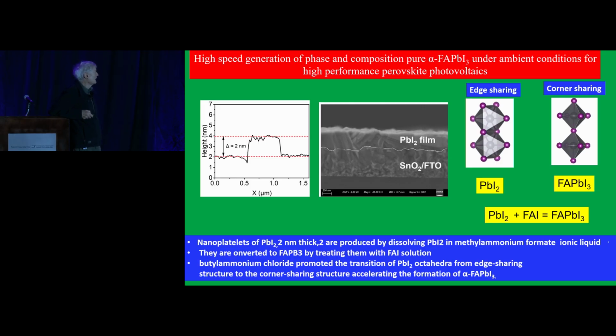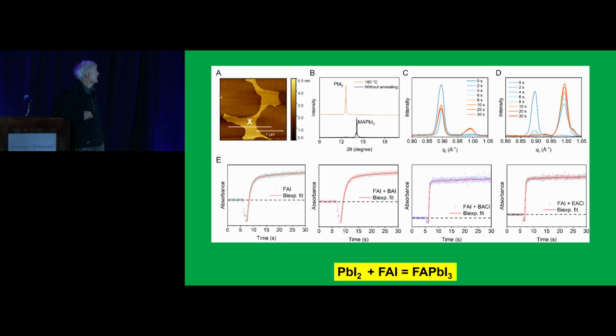So we added chloride, but we also made the films very thin so that the formamidinium could penetrate very quickly across the lead iodide. If you had a thick, planar layer of lead iodide, the conversion wouldn't work well. And so we used 2 nanometer thick PbI2 sheets. How do we make those? Very easy. You use a PbI2 conversion. You put it in an ionic liquid, methylammonium formate. And you can form these thin sheets. You first actually form the formamidinium lead iodide, but on heating it decomposes and you get these nanosheets.